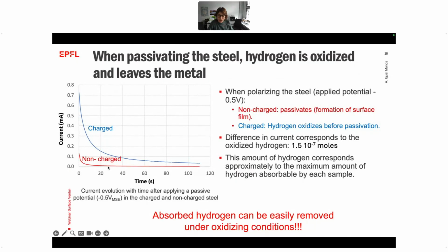Here there is no rubbing. In the non-charged and the charged sample, we see a difference in current, meaning a difference in charge during this period. What happens is all the hydrogen we have at the surface and inside the material, because of the oxidizing conditions, we are oxidizing it and it is leaving the metal. So at the end, the response of the material charged and dissolved in hydrogen is the same as the one that is only passive. So the difference in current between the non-charged and charged corresponds to the oxidized hydrogen.